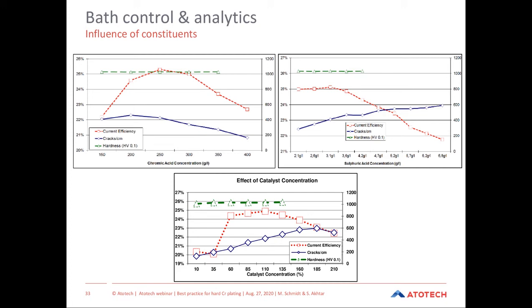On the bottom table, you see the effect of the catalyst, the organic catalyst, which is used in the HEEF process. It's mainly there to increase the plating speed, from 10 to 15% in Sargent baths up to 25%. And also it provides the high hardness and the increase of the microcrack count. You see the green line, the hardness is not changing in any of these tables. This means hardness in the HEEF process is very, very stable.